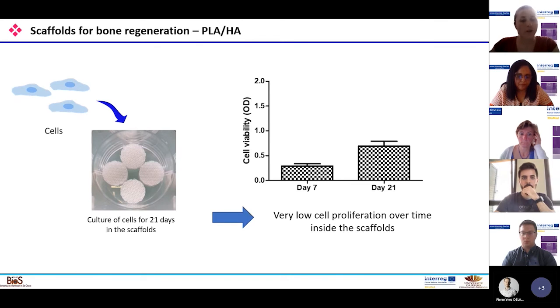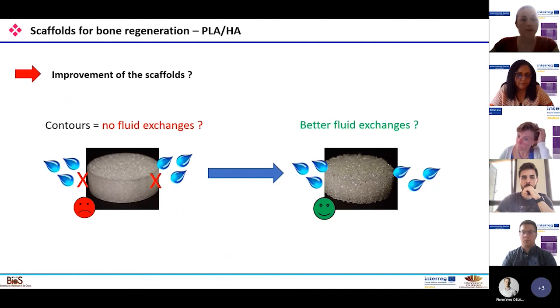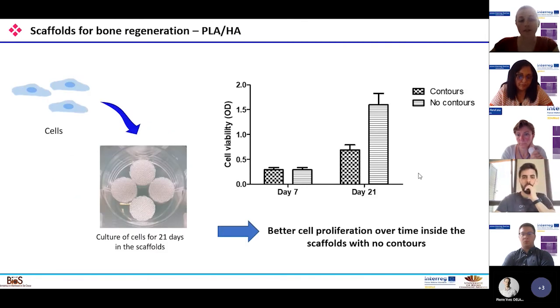We then decided to think about how to improve these scaffolds to obtain a good proliferation of the cells. And our hypothesis was to remove, in fact, the contours of the scaffolds, which could prevent the fluid exchanges and then the diffusion of the nutrients to the cells. We therefore developed the same scaffolds, but with the contours removed. And we performed the same viability test at day 7 and day 21. And this time, as you can see on the graph, we observed a cell viability which was far more important for the cells cultivated with no contours than for the cells cultivated with contours, which confirms our hypothesis to remove the contours for better fluid exchanges.